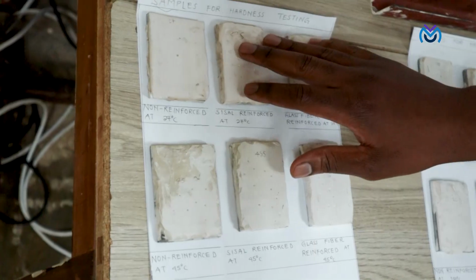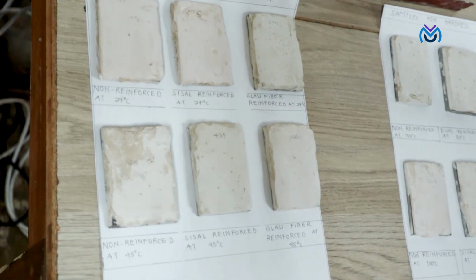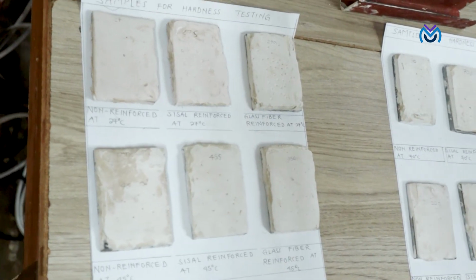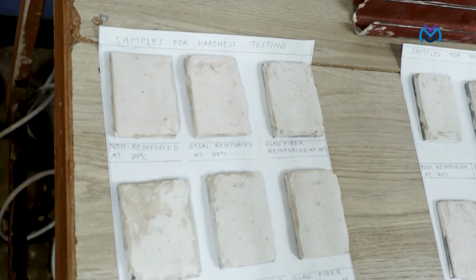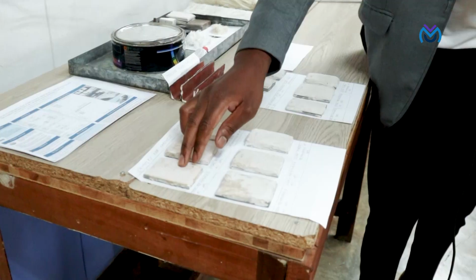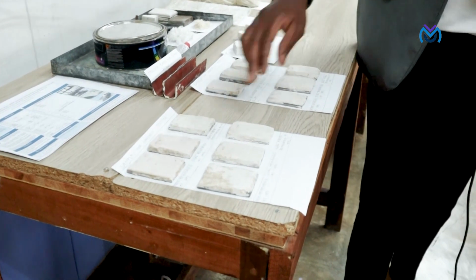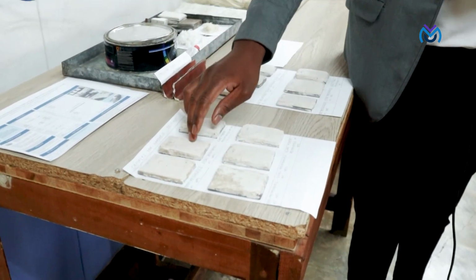So here are our samples that we prepared for the testing. For hardness testing, here are the samples at different curing temperatures to see the variation in the results. So it was basically not only about adding the sisal hemp, but also to find the best curing treatment and temperature. So we put some other samples, like at 27, we put it in the shade, curing it at room temperature. Here it was cured under UV lighting, and here it was cured in the oven, which was at 70 degrees Celsius.